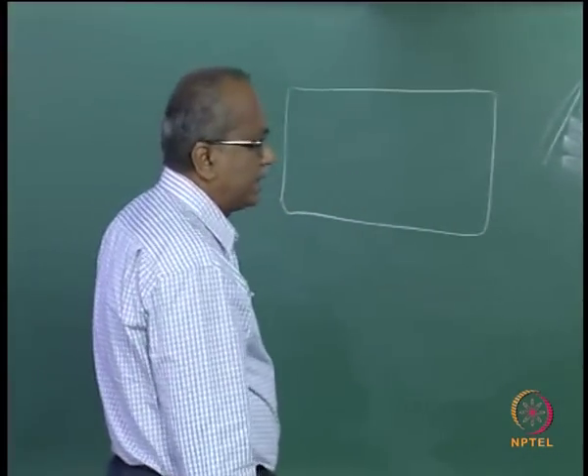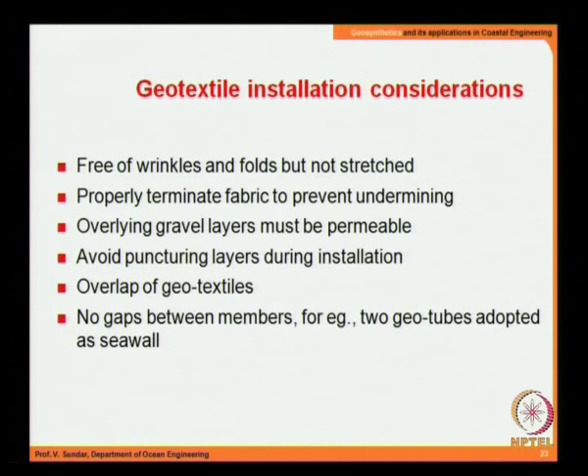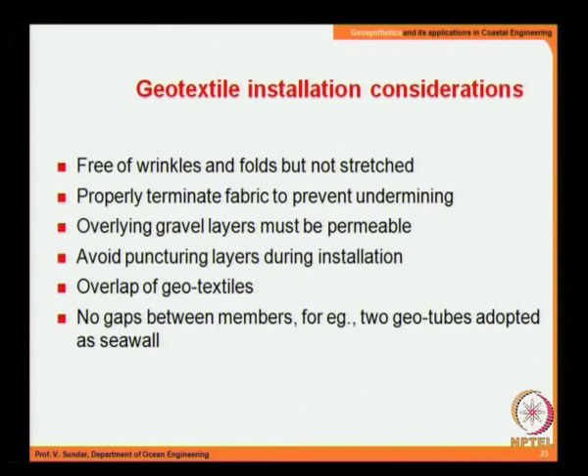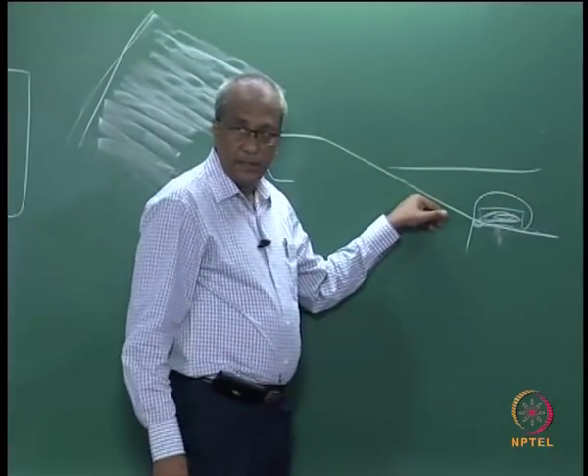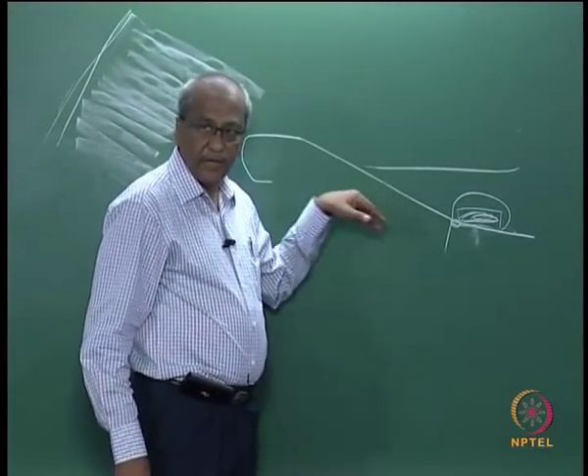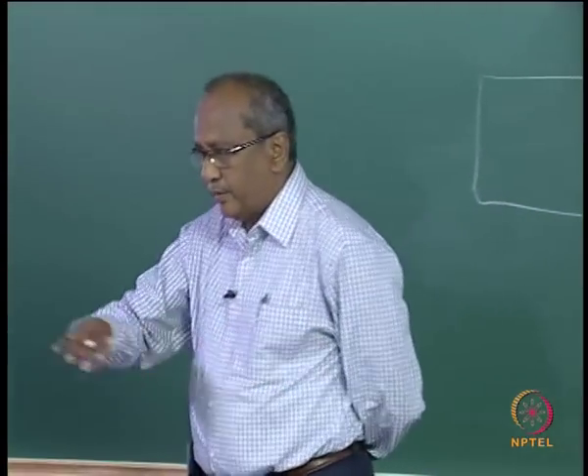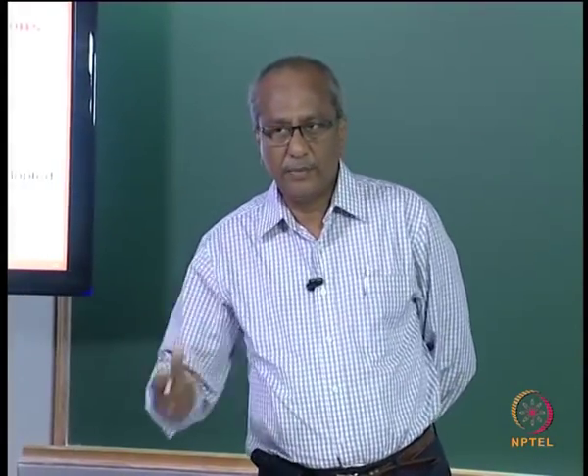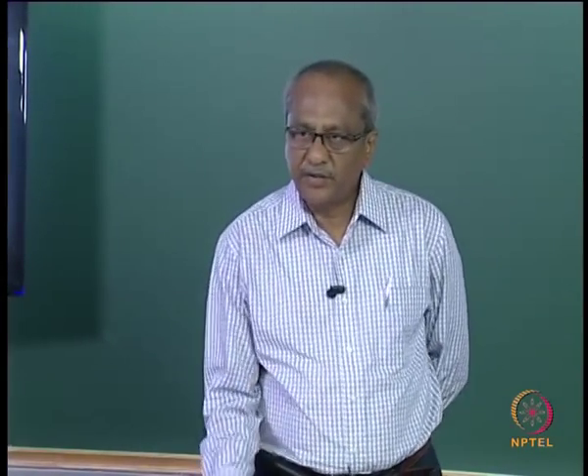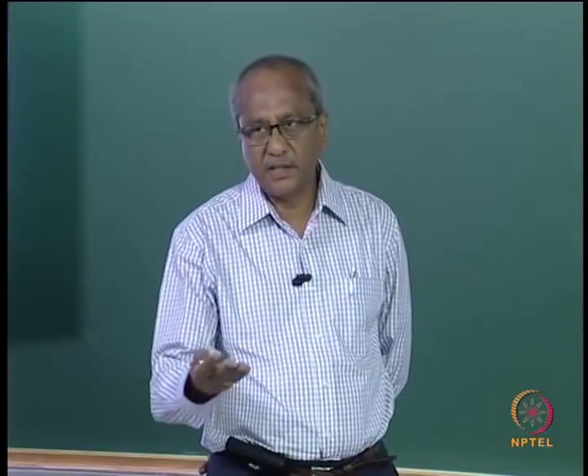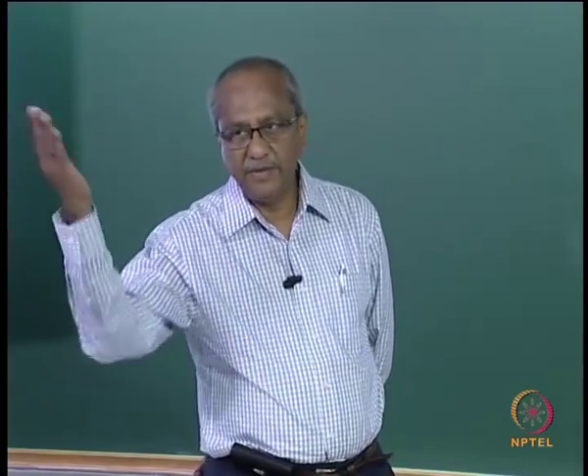Overlying gravel layers must be permeable. Puncturing is a very common issue during installation of geotextiles, which means before laying the geotextile a ground preparation is needed. You must ensure there are no sharp corners that could puncture it, because once punctured it is almost like not having the geotextile there.